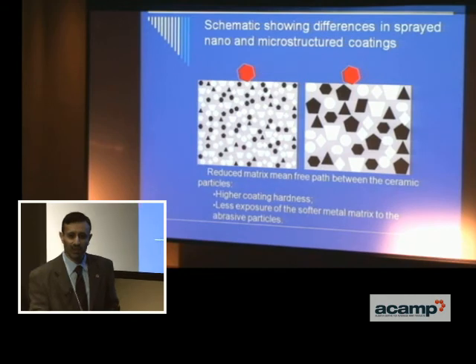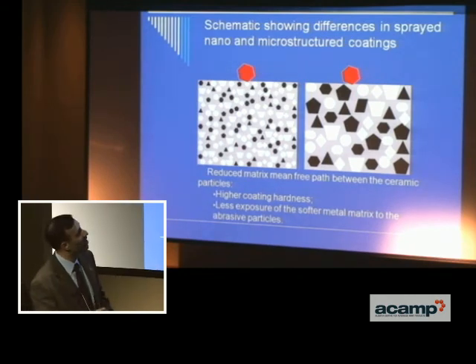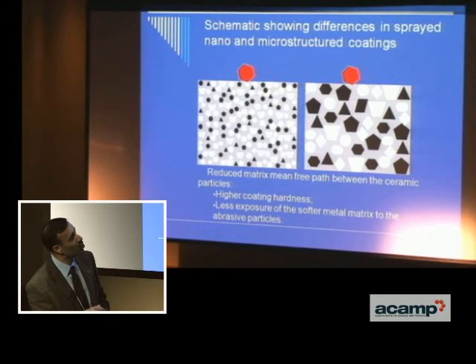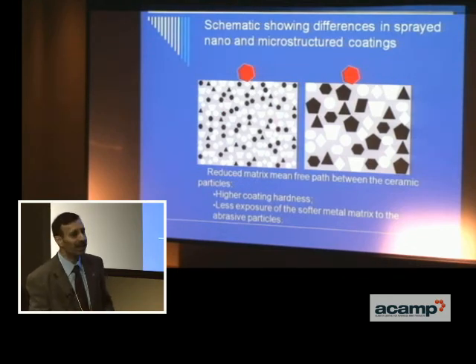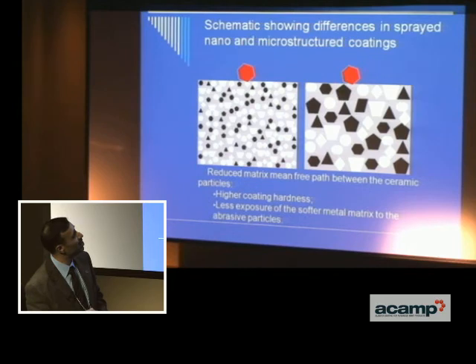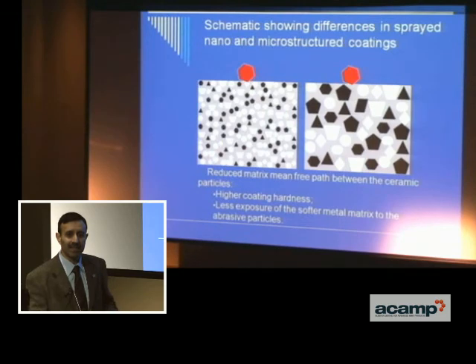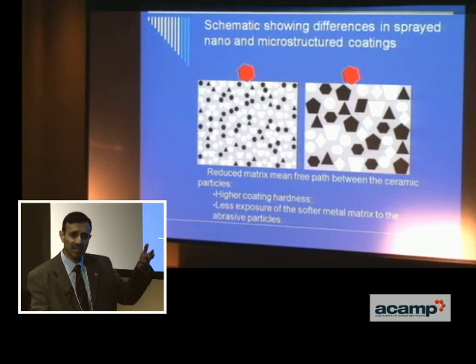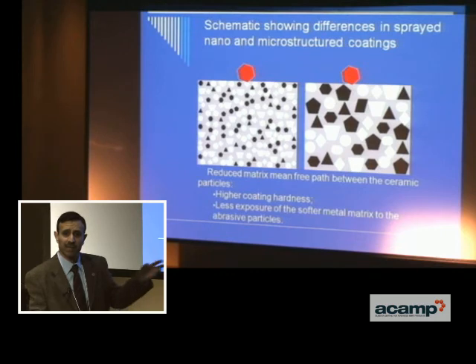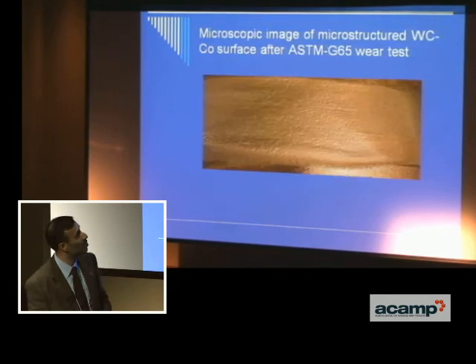So what are we trying to do here? Basically, this schematic explains that with the microstructured material we're packing much less, but with a nanostructured material we can pack much more dispersion strengthened material. It reduces the distance between the particles, and the effect is that it improves the fracture toughness of the coatings as well. What we tend to find is as hardness increases, materials normally become more brittle, which lowers the fracture toughness. But here, with the nanostructured material, we tend to improve fracture toughness as well.